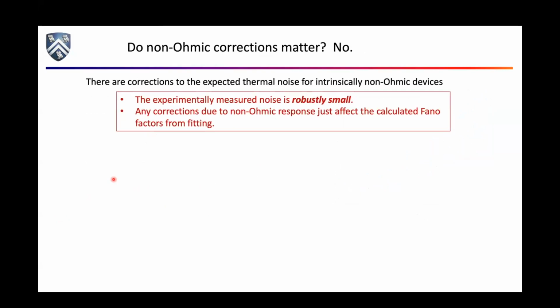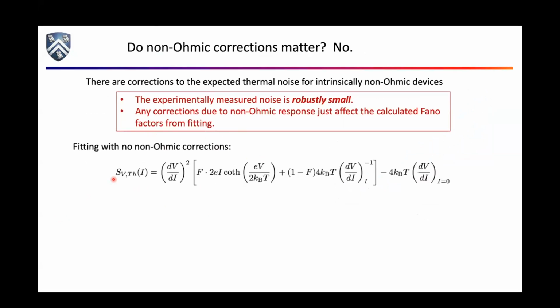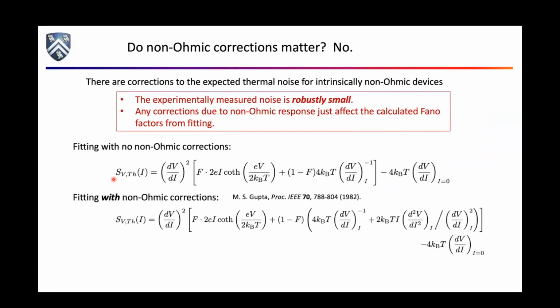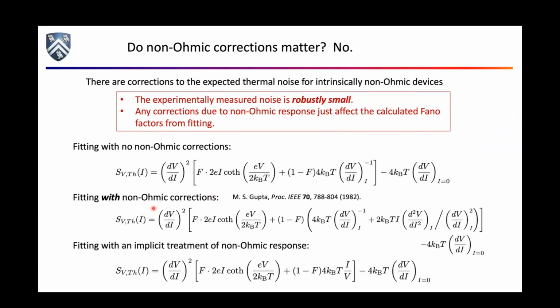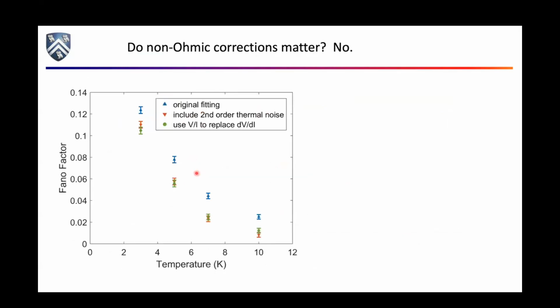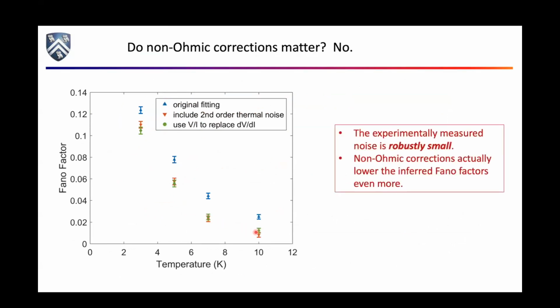You might worry that maybe my device is a little bit non-ohmic. Does that matter? The short answer, no. The noise is robustly small. If you try and correct for the non-ohmicness of the device, all it does is affect your curve fits. It doesn't affect the magnitude of the noise at all. It just affects what F you pull out. Bottom line, if you try and correct for non-ohmicness, all it does is make the Fano factors you pull out even lower. So the noise is really small; these wires are quiet.